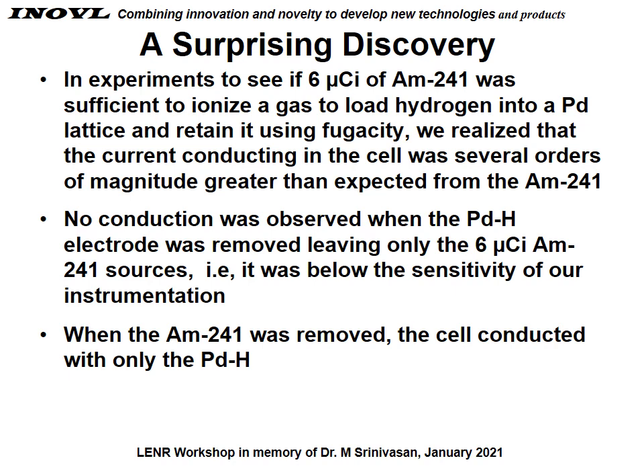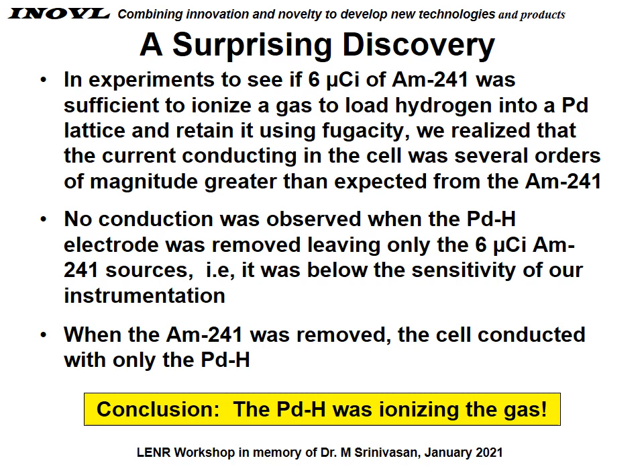During the test, we realized that the current we were conducting in the cell was several orders of magnitude greater than what we would have expected with the americium-241. So we took a test where we removed the palladium hydrogen cathode and replaced it just with a blank copper tube. At that point, we could not detect any ionization. The americium-241 was not producing enough ions. Then we took the cell where we had emptied the americium-241 and had only the palladium hydrogen cathode in there, and the cell conducted. So the conclusion was that the palladium hydrogen was ionizing the gas.